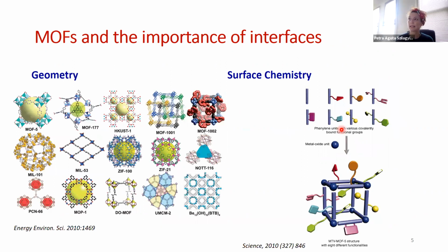And there are two different aspects, one of which I just mentioned: this kind of templating effect by the pores. In principle, we should have atomistic level control on the particle shape and size that's grown inside the pore. But the other and perhaps even more important aspect is that, as I've already mentioned, these are hybrid materials. They have both inorganic and organic building blocks, so we essentially are tapping into both of these disciplines. And we know that the geometry and the valency of both inorganic ions or clusters, as well as organic linkers, may be very diverse. And so when we are combining them, we can really unlock a huge multitude of different possible pore shapes and sizes. And so therefore we can really grow different kinds of particles in them.